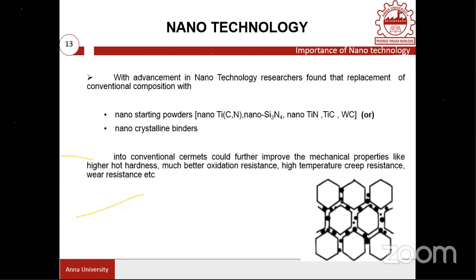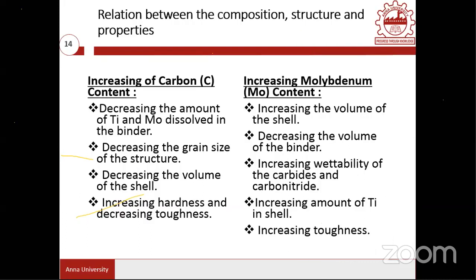So sometimes you can also include this material inside the core. That is a different issue. Okay, so here, what are all the properties that one can improve by adding this nano-based material as a secondary carbide or secondary nitride or secondary boride? The hot hardness would be improved, and there would be much better oxidation resistance, high temperature creep resistance, and wear resistance would be improved. Now here, specifically, are some of the alloying elements we used to add.